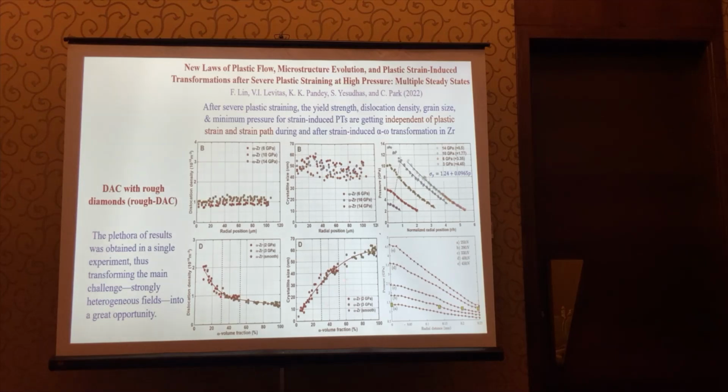And these curves have a very important practical consequence. For example, look here, even at 14 GPa and large plastic deformation to reach 14 GPa, we cannot get crystallite size below 40 nanometers. But during phase transitions, we have 5, 10, 20 nanometers, and pressure was below 2-3 GPa. So actually, phase transformation is, in this case at least, a more effective way to refine microstructure than plastic deformation.